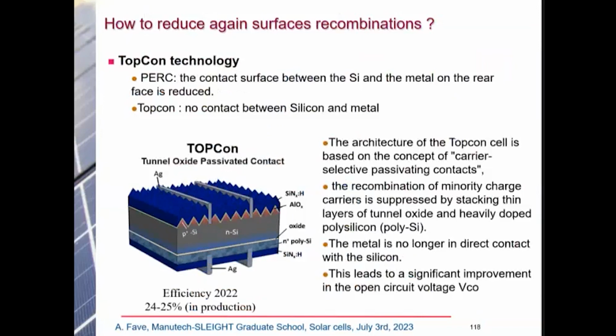So this architecture is based on the concept of carrier selective passivating contact. Recombination of minority charge carriers is suppressed by stacking thin layers of tunnel oxide and heavily doped polysilicon. Okay. This leads to a significant improvement in the open circuit voltage.